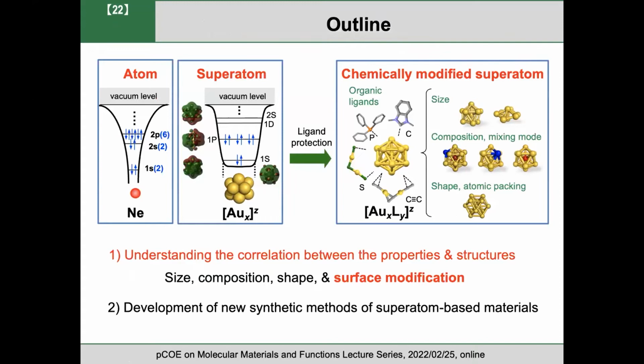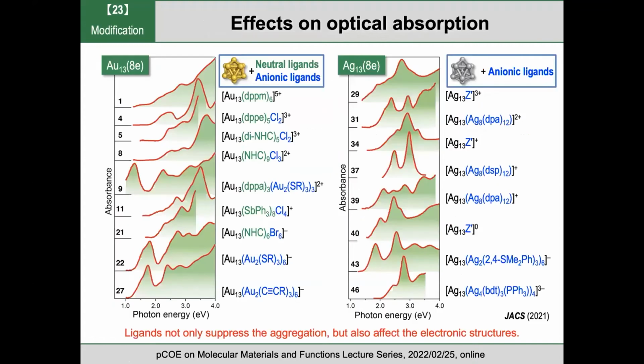Okay, so then let me move on to the surface modification effect. The primary role of the surface is the suppression or prohibition of the aggregation of the metallic core. Okay, but the ligand plays more roles. Actually, these are the optical spectra of gold 13 and silver 13 protected by different types of ligands. And the total number of electrons is always 8 in both systems. But as you can see, the optical spectra are very, very different. So the ligand plays a very important role in the electronic structures.